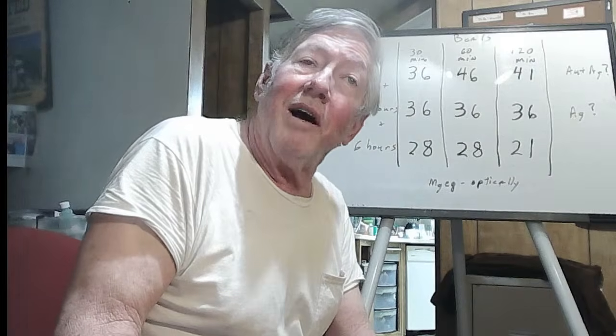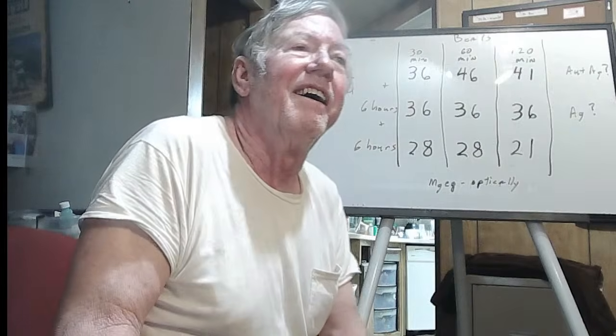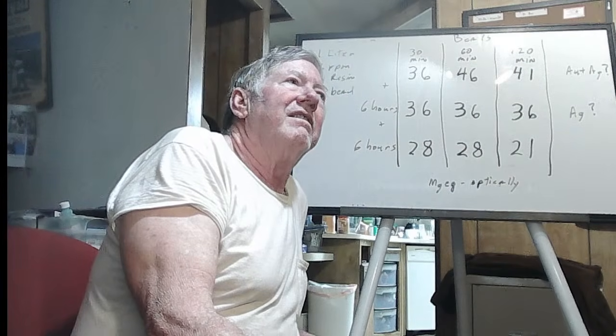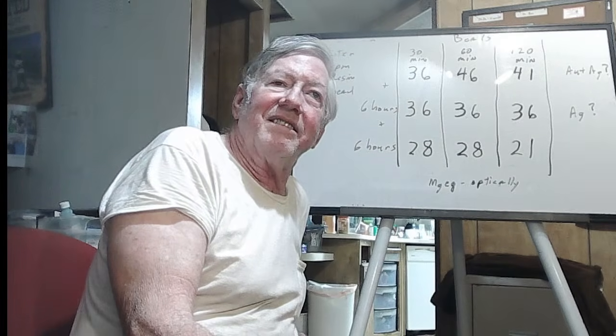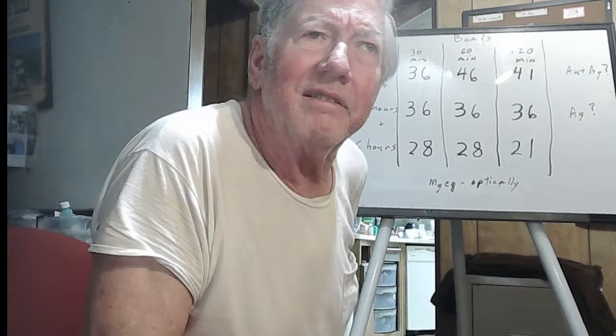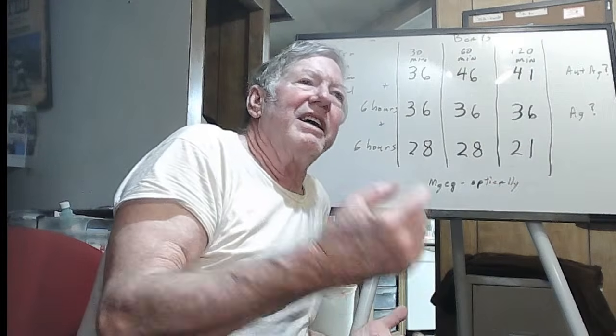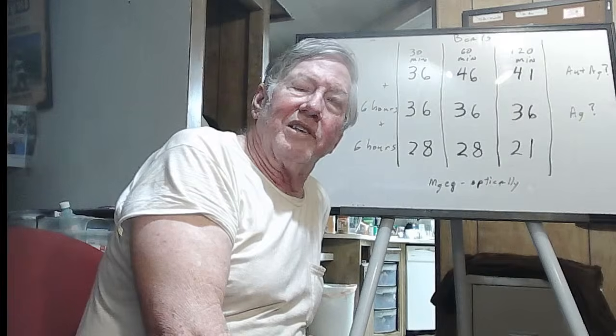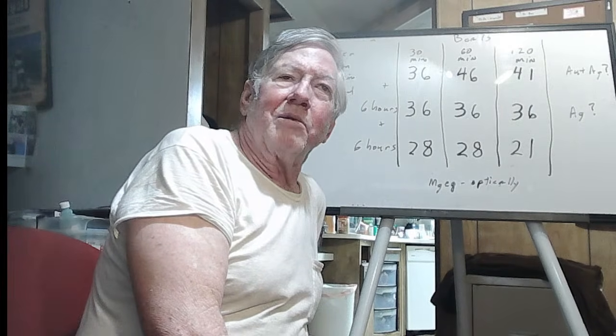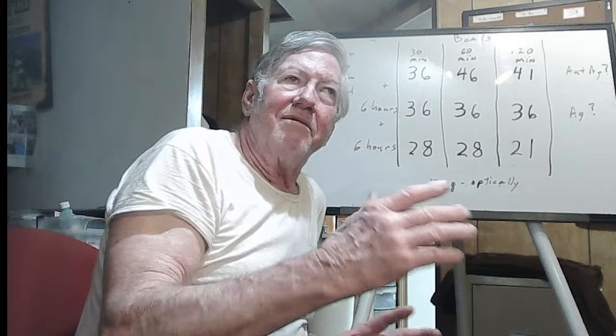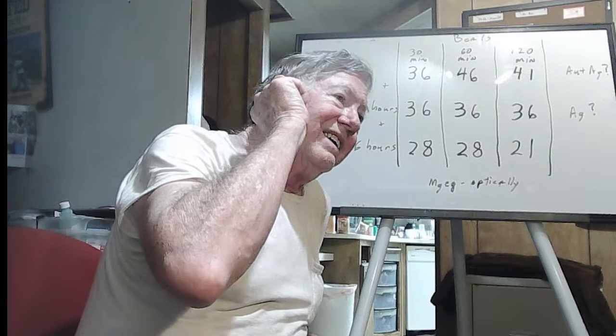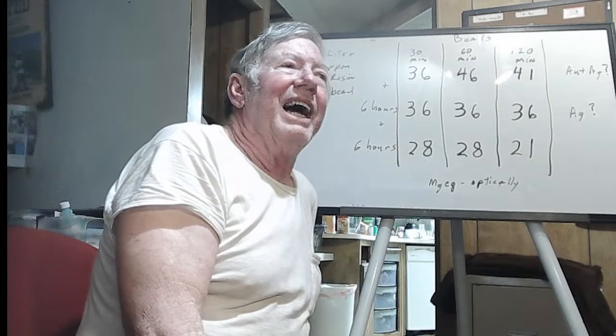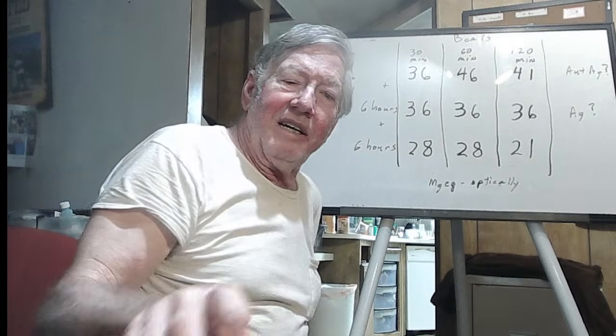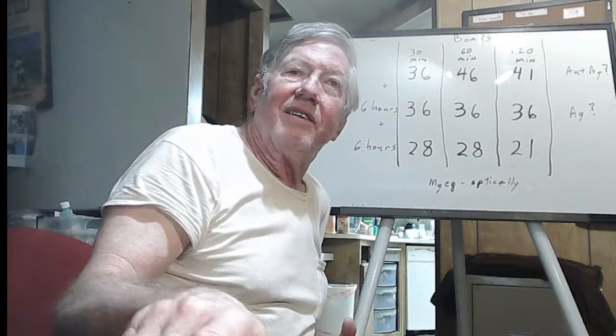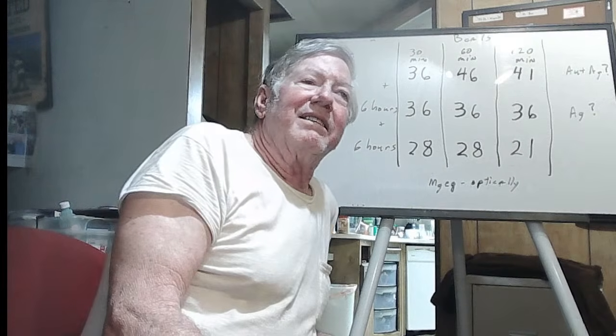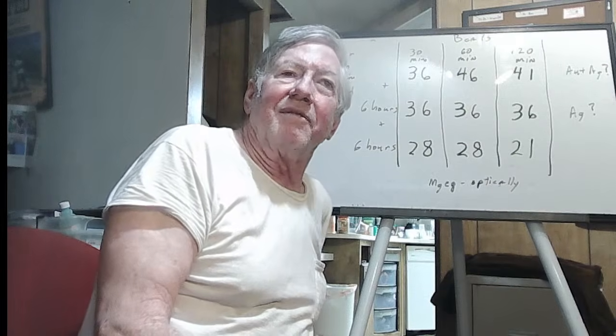Unfortunately, it's not cooperating. Okay. Now, the copper wire test does seem to work pretty well, though. If you just take a clean copper wire and stick it in the leach solution at about 10 parts per million, you'll see a significant coating of gold on the wire in about 30 to 60 minutes. At the normal leach concentrations, which would be about 30 or 40 parts per million, it's a lot faster than that. You can get a good, clean result in like 15 minutes.